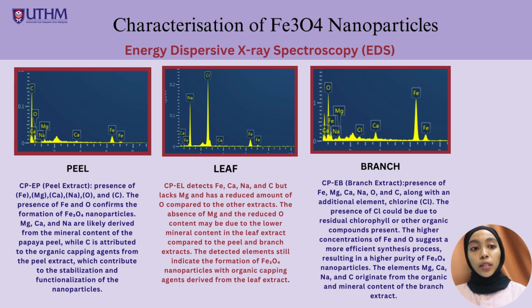Branch extract presents all the same elements, with an additional element which is chlorine. The presence of chlorine could be due to the residual chlorophyll or other organic residual compounds present. The higher concentration of iron and oxygen suggests a more efficient synthesis process, resulting in a higher purity of iron oxide nanoparticle. The elements magnesium, calcium, sodium, and carbon originate from the organic and mineral content of the branch extract.